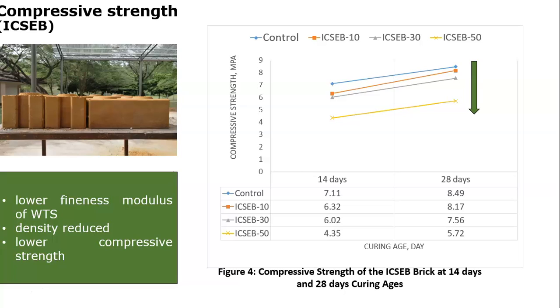A low fineness modulus of the water treatment sludge has caused a reduction in the density of brick, which leads to the lower compressive strength. Nevertheless, all brick samples have exceeded the strength of 5 MPa, which satisfies the minimum limit of BS 3921, except for ICSEB 50, which was tested at 14 days period of curing.